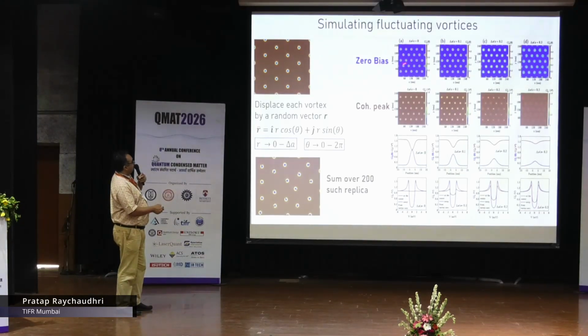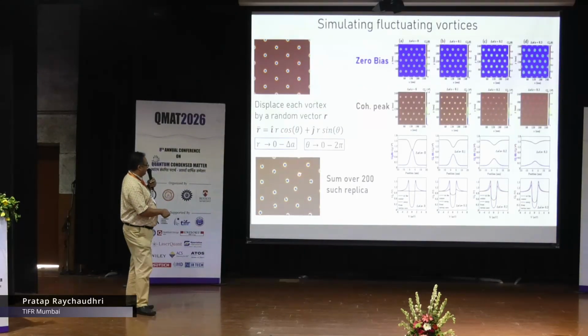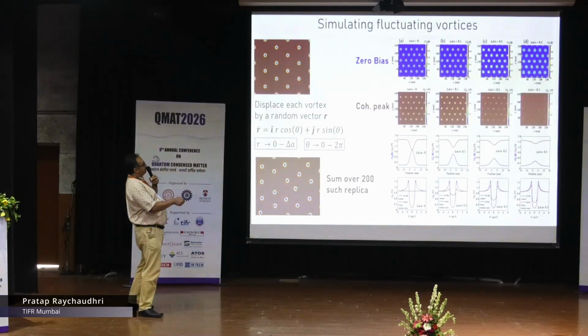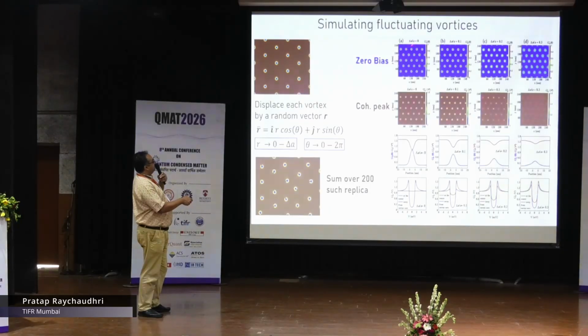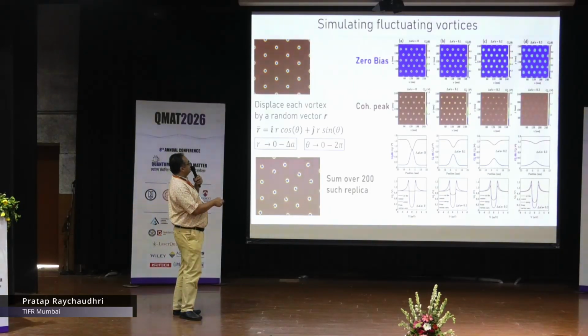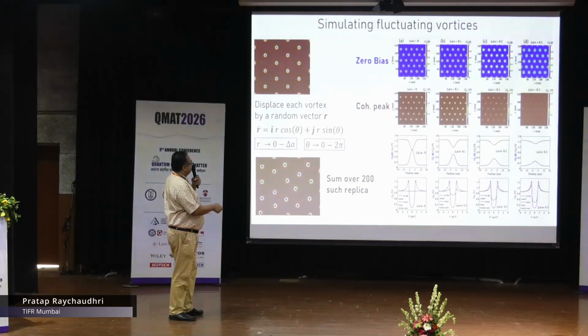Now, when you do this, A is my lattice constant and delta A is this maximum vibration amplitude. In my simulation, you see that as delta A by A increases, the zero bias conductance map gradually gets more diffuse, the conductance minima get more diffuse, and similarly the coherence peak map also gets more diffuse.